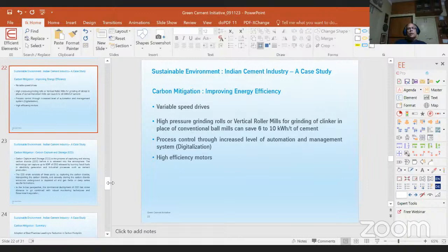Staying with carbon mitigation, we are on improving the energy efficiency. I mentioned we can use the variable speed drive. You can optimize your power consumption. You can use high pressure grinding rolls and vertical mills for clinker grinding also, not only in the raw grinding. In the earlier slide, we have seen the raw grinding. In the clinker, that is clinker to producing cement, you can reduce 6 to 10 units. Then process control, you can employ the digitalization concept. You can optimize the fluctuations in fuel and fluctuations in the raw. And these are small, important, but precious steps; the contribution may not be huge, but still it contributes, and it is measurable, and it is significant as far as the environment is concerned.